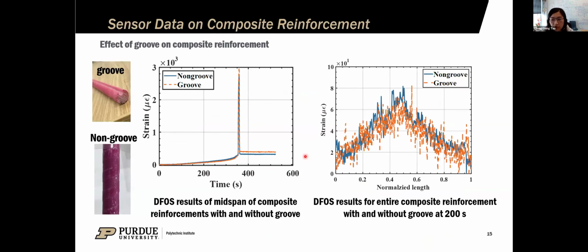So as I mentioned earlier, we have two protection strategies for our fiber optic sensors, like we created a groove on the rebar. But we want to check if this groove will affect the performance of the composite rebar. So we compared the result of the rebar strain with the groove and without the groove, and we found that the two results match quite well. By comparing and analyzing the strain data on the rebar, we found the slim groove doesn't affect the strain too much, so we can put the silica tube in the groove to better protect the fiber optic sensors in the future.